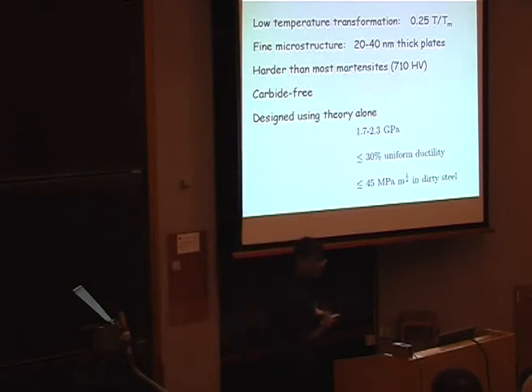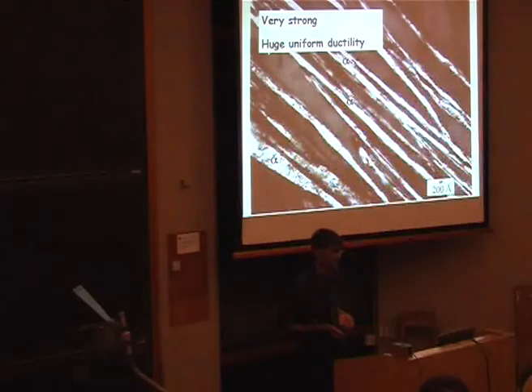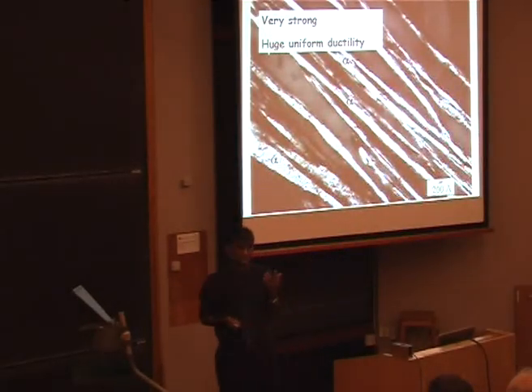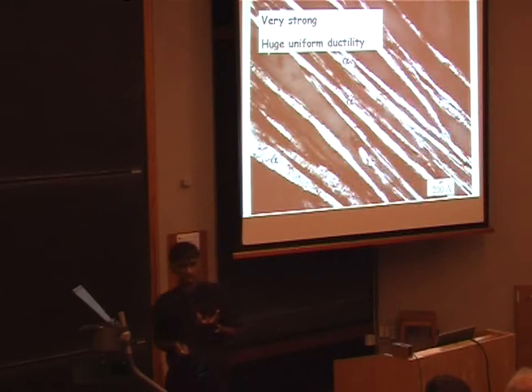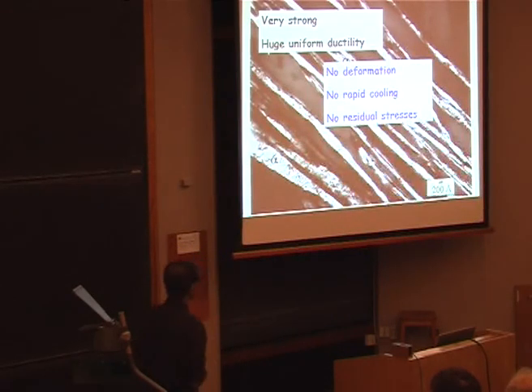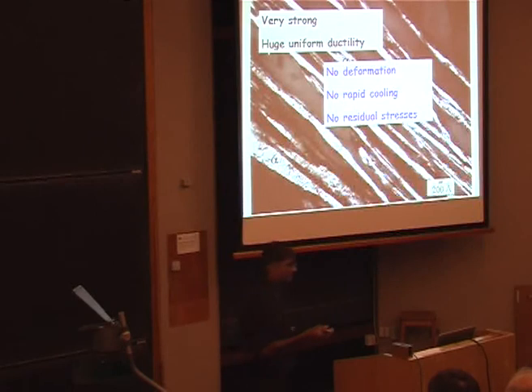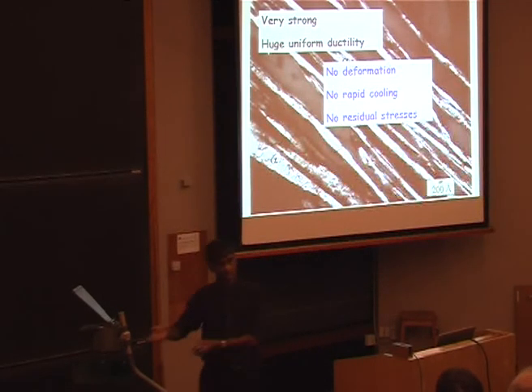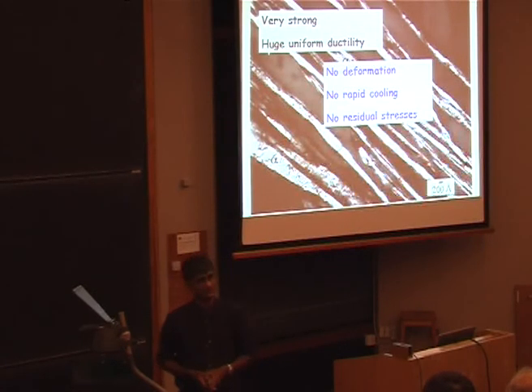We haven't done anything here to control non-metallic inclusions, etc. It's ordinarily produced steel. So we've got very high strength, a huge uniform ductility. We haven't put any deformation into this material. It's produced by phase transformation. There's no rapid cooling. Because it's a slow transformation, you can take the steel from 1,000 degrees centigrade, put it into a pizza oven, and leave it there, and it will transform. So there are no residual stresses from rapid cooling.